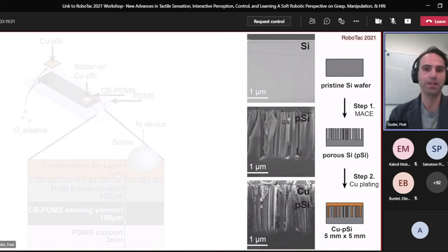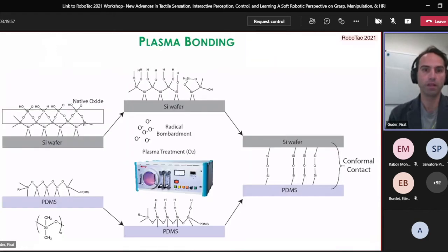But essentially, without nanostructuring the silicon, the copper layer just basically peels off on its own. Once we nanostructure the surface through a chemical process, then we can create interlocking structures within the substrate or underneath the surface, and the contact becomes incredibly robust. And we do plasma bonding to attach the silicon wafer to the silicone rubber. We just do oxygen plasma and then literally just attach them together, and then they're bonded and covalent bonds are formed.